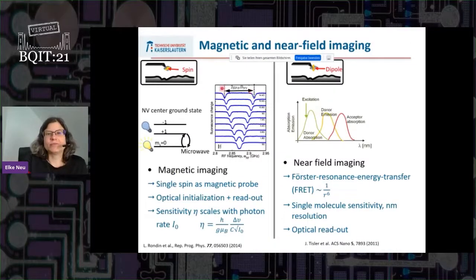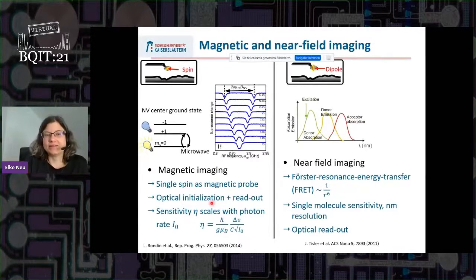How does the color center work? On the one hand, in the ground state of this NV center, you have three different spin states, the 0, the +1, and the -1. And due to internal dynamics, if the system is in the 0 state, it will emit a brighter fluorescence than in the two other states. You can drive the transitions between those states with a microwave and read out the spin state then optically because of this difference in fluorescence. It is what we call optically detected magnetic resonance, and especially these +1 and -1 states undergo a Zeeman shift. So the difference between the transition from 0 to +1 and 0 to -1 tells you which magnetic field has been applied to the NV center. Like this, you can use a single NV center as a sensor. The sensitivity scales with the photon rate, so you always need to get a good optical readout.